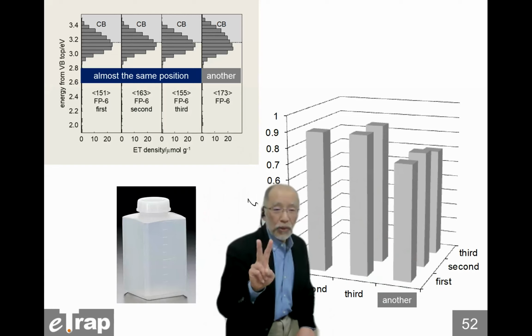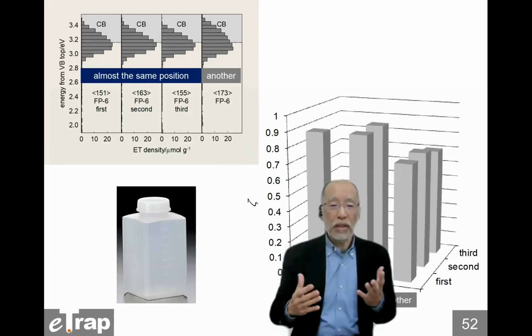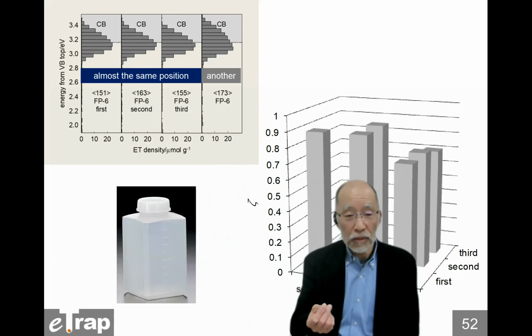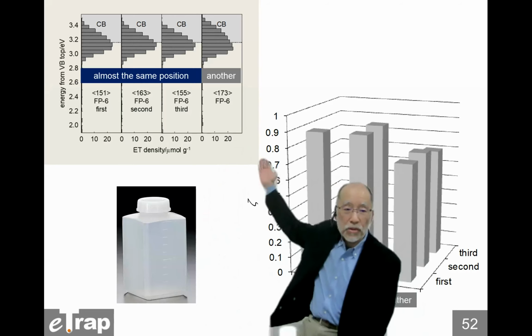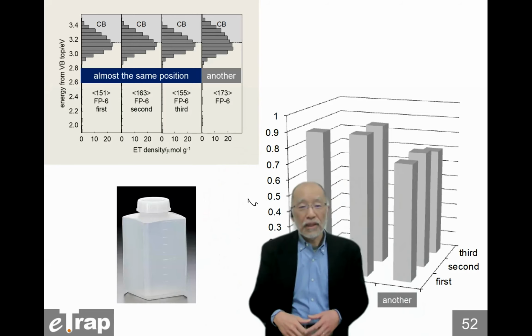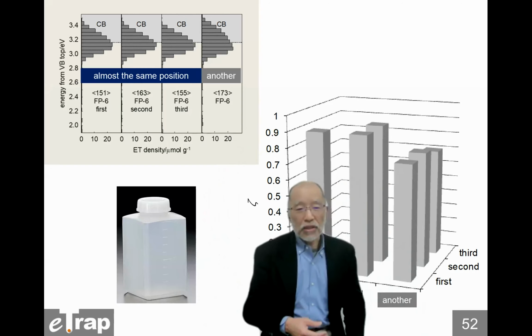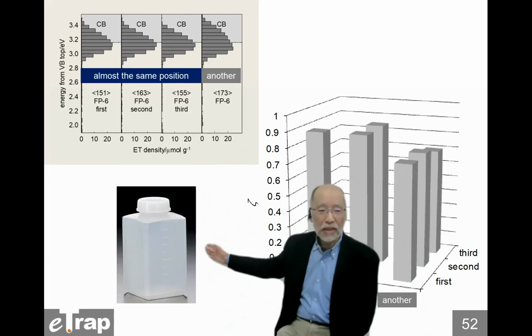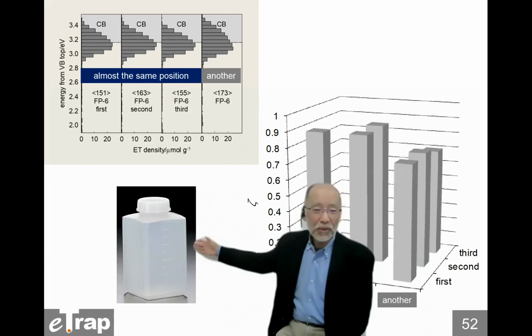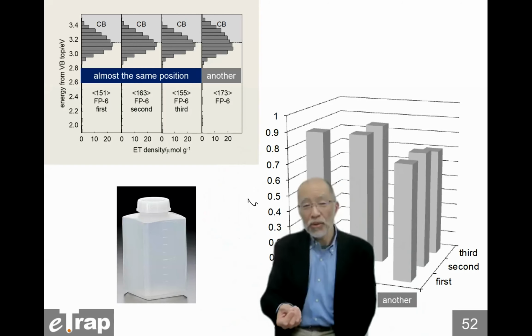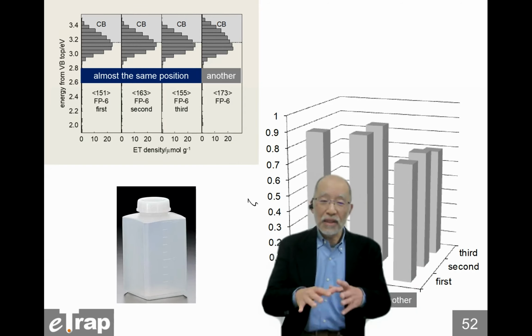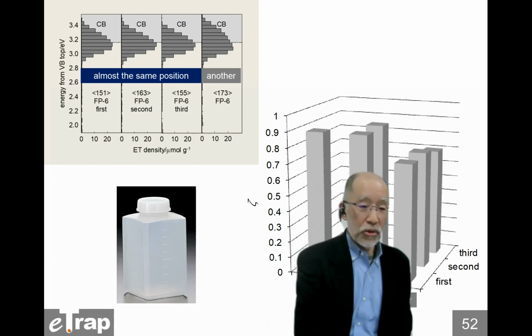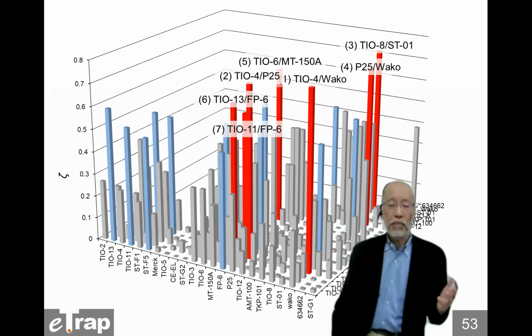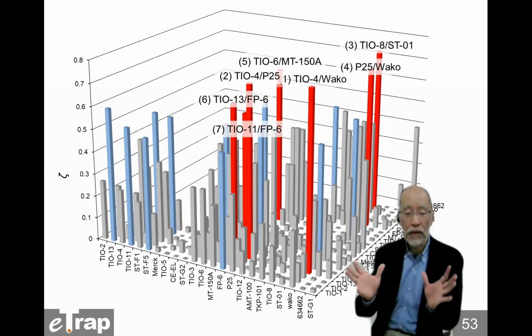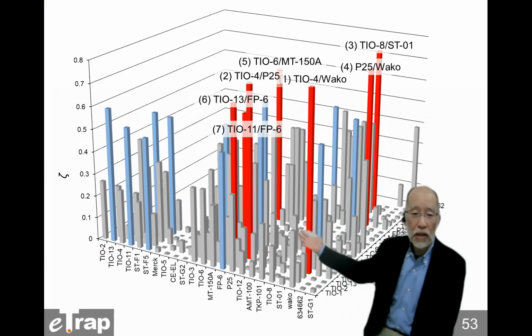So there are two points. One is that this technique is very, very sensitive, especially to surface structure. And the second point is that for such a powder sample in a bottle, even in the same bottle, in the same package, with the same code name, there is some heterogeneity in the structure. And this is the result for pairs of commercial titanium oxide samples.